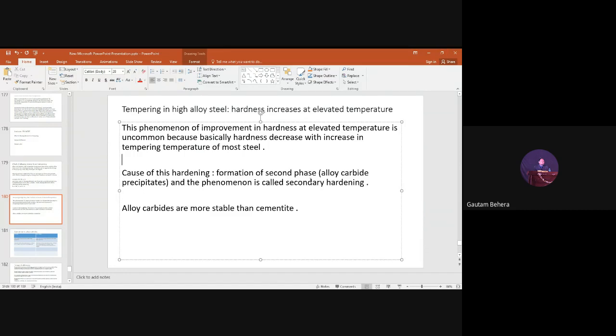But in the case of carbon steels, this does not happen because there are no alloy carbides, basically, right? And there is an interesting line: alloy carbides are more stable than cementite. This is a very good thing to remember. Alloy carbides are more stable than cementite. Suppose you have a steel having precipitates of cementite, cementite networks or cementite particles. They are not actually stable. If you take the steel to a high temperature like 750 degrees centigrade or above, they will become soluble in the austenite phase, right? Because they are unstable, they get dissolved.